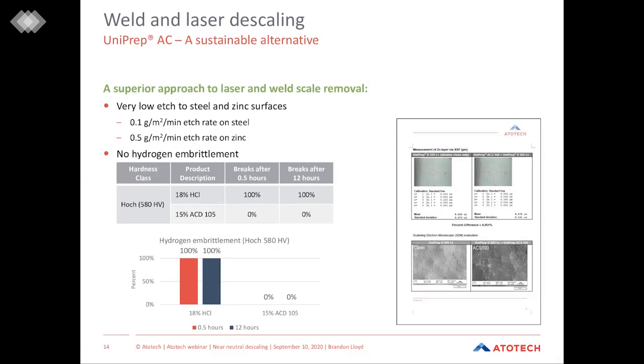So Uniprep AC also offers a very low etch rate for both steel and zinc surfaces. At new makeups, what we've seen in some of our lab evaluations is an etch rate on steel of 0.1 grams per square meter per minute. And for zinc surfaces, being galvanized substrates and the like, an etch rate of about 0.5 grams per square meter